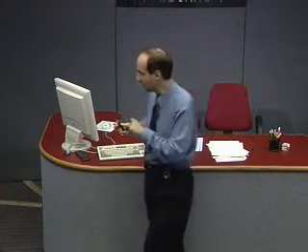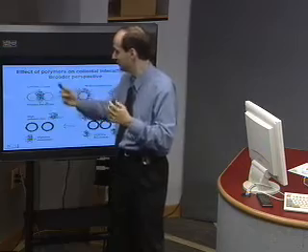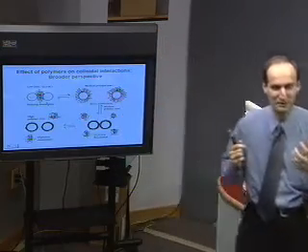Now, on the other hand, bridging is actually fairly useful. This is one way to glue the particles. Imagine you make some structure, and then you want to stabilize it. You add some polyelectrolyte which sticks to the particles, not too much. Then these two particles stick together, and the polymer is really bridging them very hard. There can be polymers like that, very sticky polymers. When you do that, you can stabilize the structure that you just made. So in terms of colloid engineering, bridging can be very useful, but really as a glue. This is the way to glue two particles together after you have put them in the place where you like them.